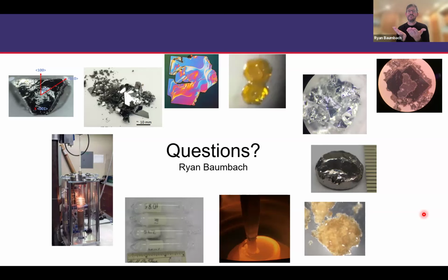There's a way to bend the tips of it so it makes a fishtail that's bent up. I could send you a picture of that if you're interested. And then the advice is to move fast, okay? You don't need to have the arc on the part that you want to weld for very long. You simply run it across the edge of that tip, let it cool down, then you run it across the edge of the tip again, let it cool down. Those processes will take maybe 5 seconds, and that's fast enough to avoid doing anything to the material inside.